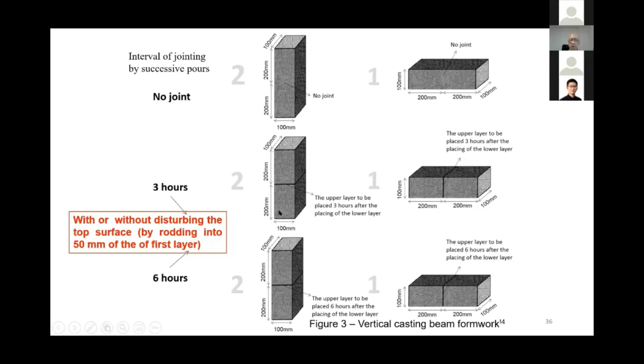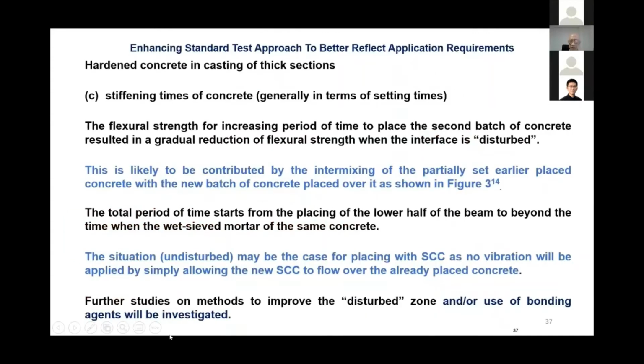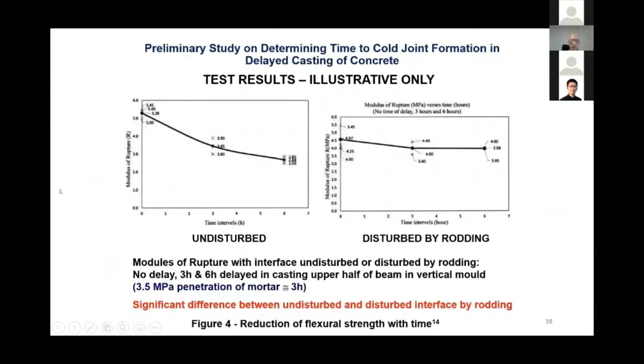In the laboratory, the way we disturb it is using a rod to poke through 50 mm. We put another 100 mm concrete on top, push in, mixing with the next 50 mm and create a weak zone, and do the same after 6 hours. So when we do that, this is now what happened to the test result.